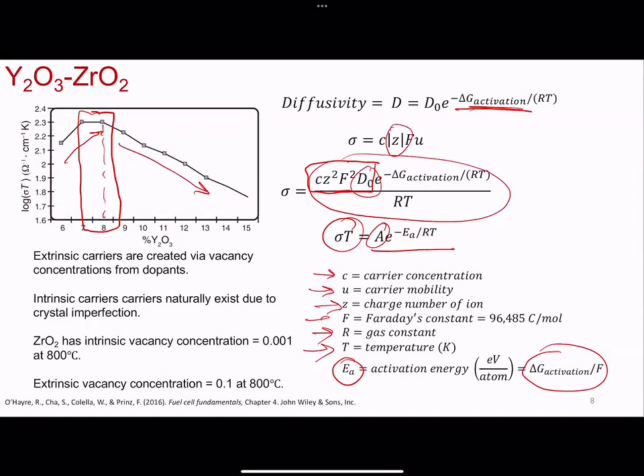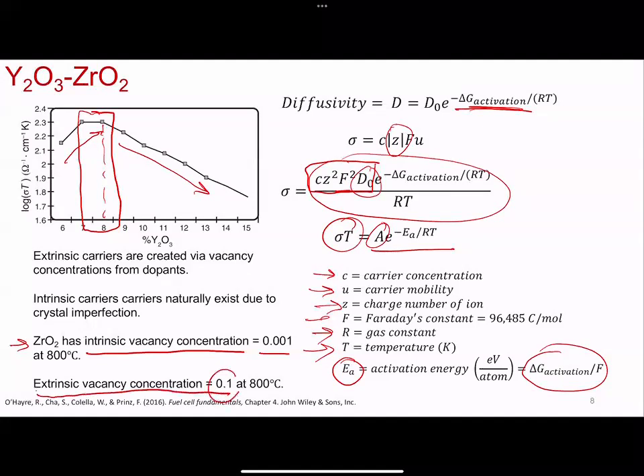So Faraday's constant is all floating in there. But that's all to say, zirconia, if you just have zirconia at 1,000 degrees, sorry, 800 C, some elevated temperature, and you say, okay, O2 minus moves. The intrinsic vacancy concentration that you have there is 0.001. That's the concentration. The extrinsic, if you substitute in with, let's say, 8 moles of yttria, now you've increased the concentration by 100-fold. So you've increased ionic conductivity by increasing the vacancy concentration by just substituting in with yttria.